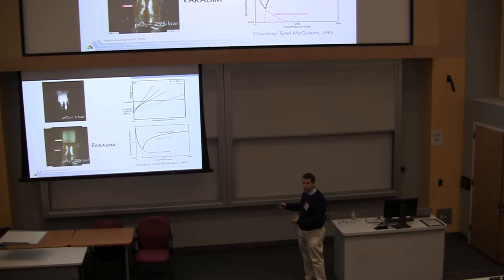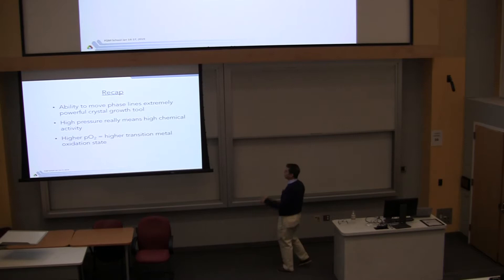And here's some phase lines that separate copper oxide CuO, which is copper 2, Cu2O, cuprous oxide, which is copper 1, and copper metal. So we just have two different equations here plotted in this diagram. Here you can see that as you sit at a fixed pressure and increase the temperature, you go across this line like this. And so you're reducing the material. And if you go along this direction and you go at a fixed temperature and increase the oxygen pressure, then you oxidize it.